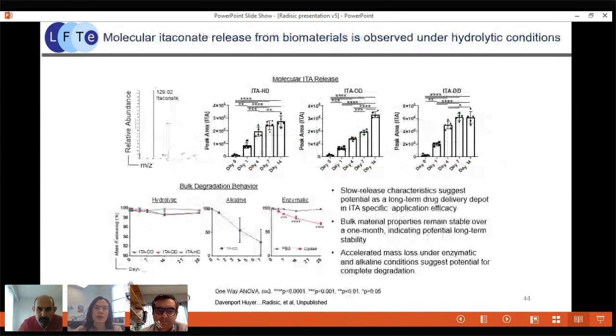And then he also was able to demonstrate that he has a slow and sustained release of itaconate from these different materials, that you can have accelerated degradation under, for example, alkaline conditions, such as those that are present in the peritoneum, and that you can also slightly accelerate this degradation if you use enzymes, such as lipase. However, bulk material properties of these new polymers remain stable over 1 month, indicating potential long-term stability.